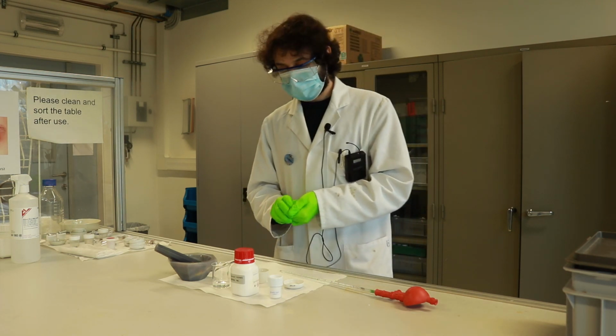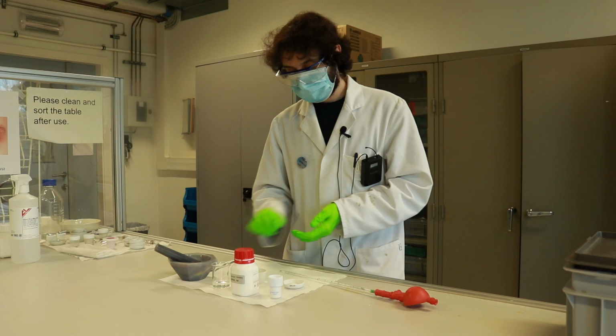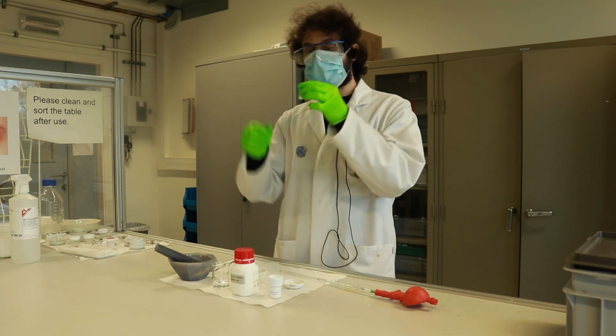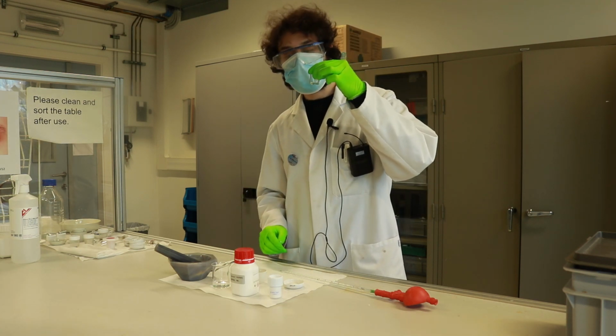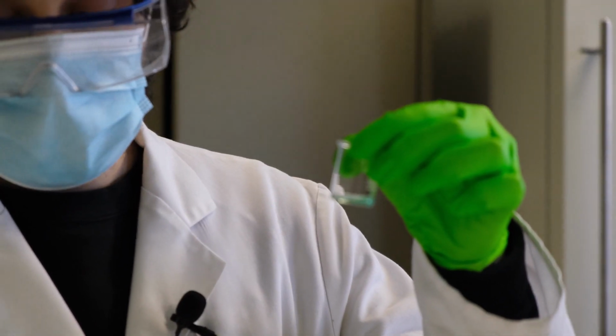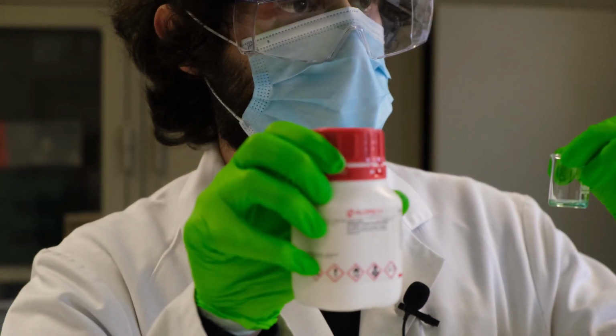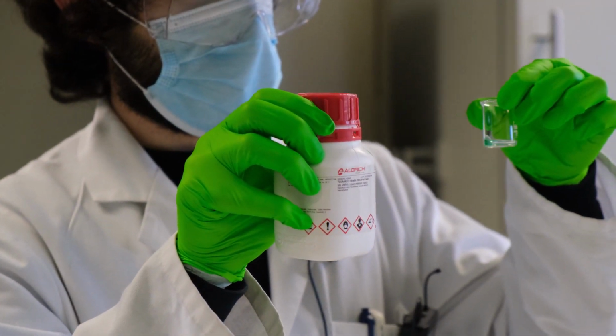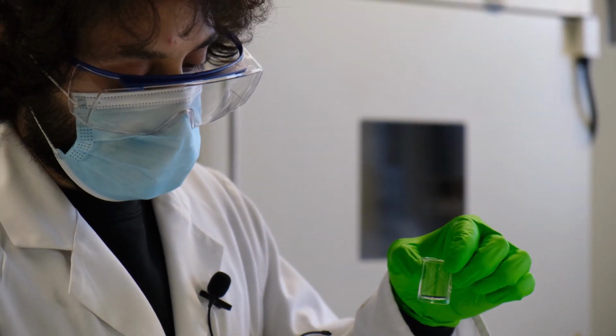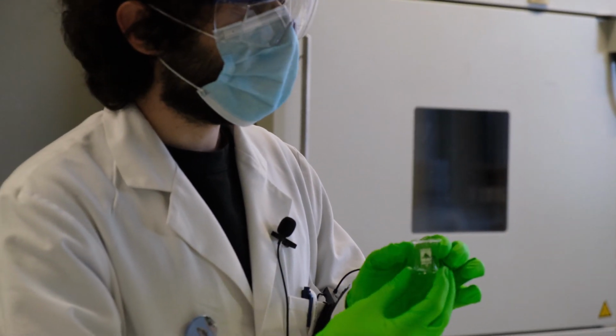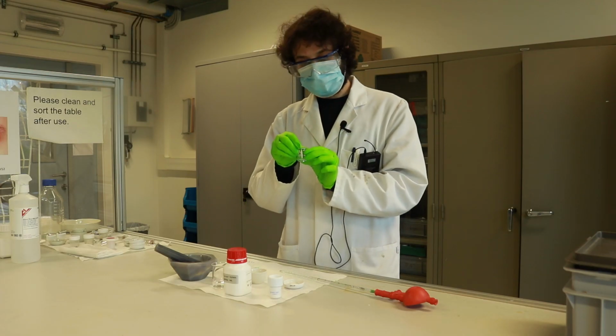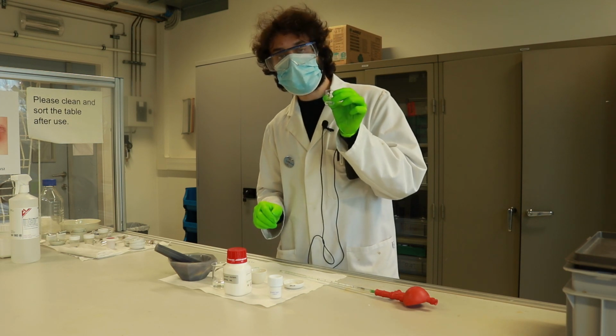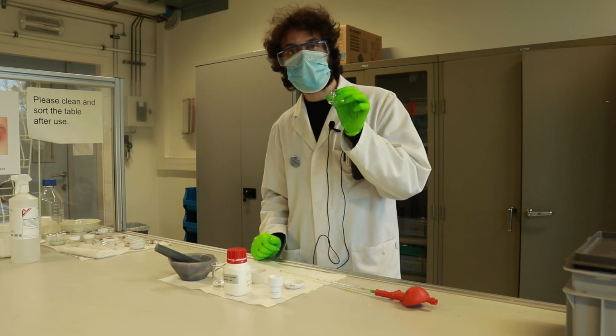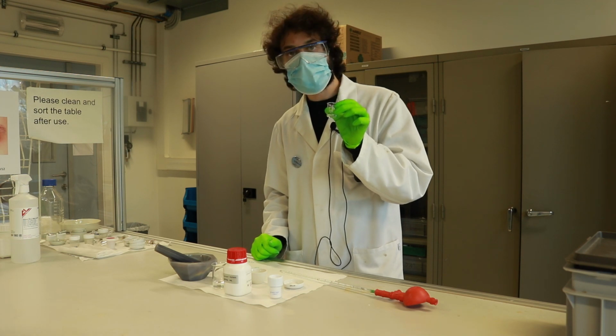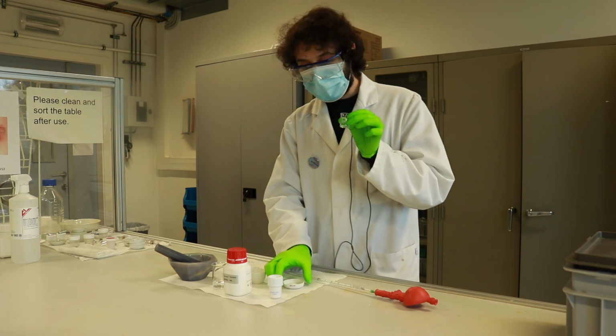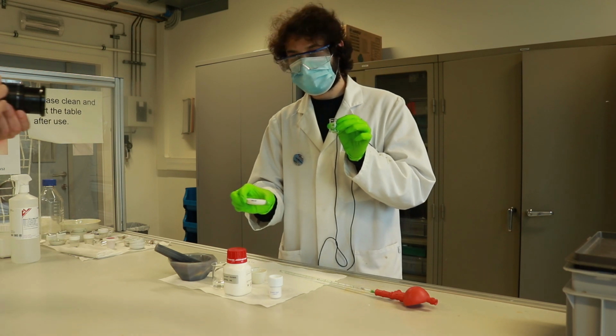In the next step, we prepare our catalyst. So in here, I've dissolved a specific amount of my nickel precursor. In this case, I'm using nickel nitrate hexahydrate. The amount will correspond to the number of moles of nickel I would like to deposit on this sample. I've dissolved this amount of nickel in a specific amount of deionized water that corresponds to the pore volume of my sample, of my carrier over here.